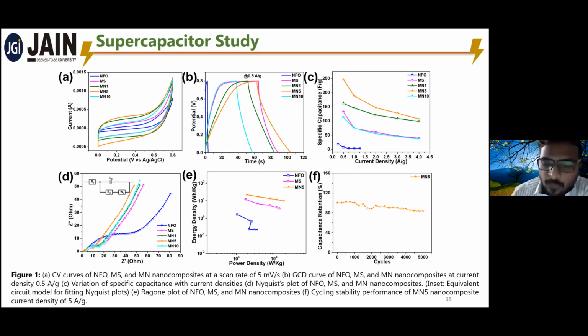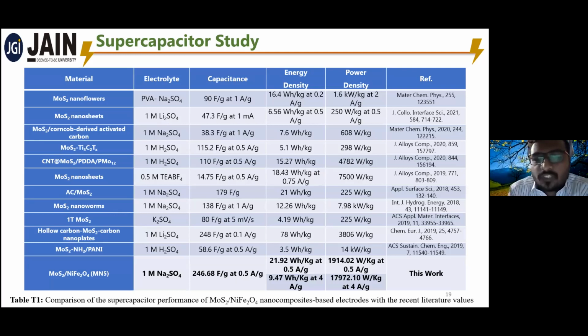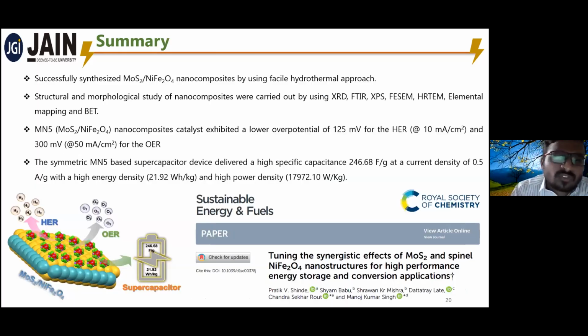The energy density and power density of the material are also higher compared to all the previously reported literature. The material shows a capacitance of around 246.68 farad per gram at 0.5 ampere per gram. The energy density is around 21.92 watt hour per kg, while the power density is 1914.02 watt per kg at 0.5 ampere per gram. This is much superior to recently published reports.